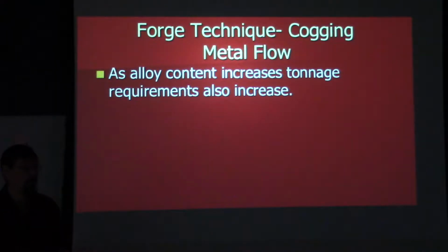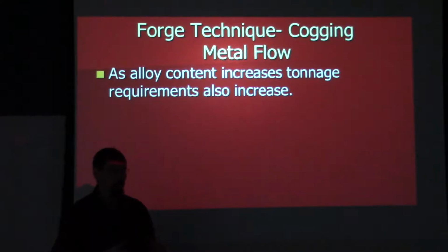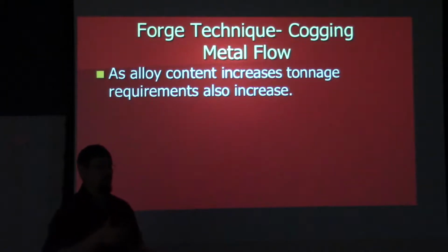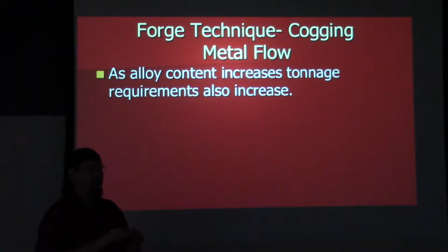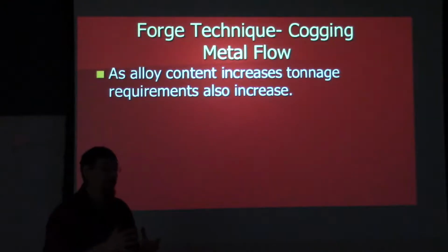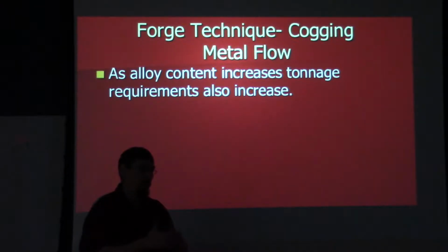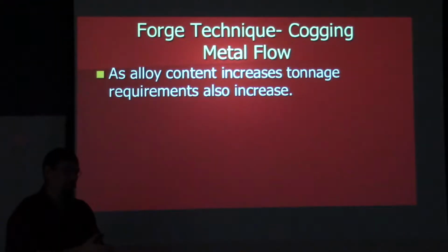The one other thing is that if you're doing a lot of forge welding, which was very common, because before you had electric welding, everything was put together by forge welding processes, and I showed that in our first video, or our first lecture. Wrought iron, with all that iron silicate, because it melts at a lower temperature than the iron, is actually self-fluxing, so that you can take these two pieces that are at, say, 2,500 degrees, the iron component's still solid, but you've now got a liquid layer of iron silicate, which is protecting the iron from oxidizing. So if you design your joint properly, you bring the two pieces together, you start to hit them, the liquid iron silicate is forced out of the joint, and you've got two clean pieces of iron that come together, and then they'll make that bond that we talked about. So they like it for that as well. Cool.